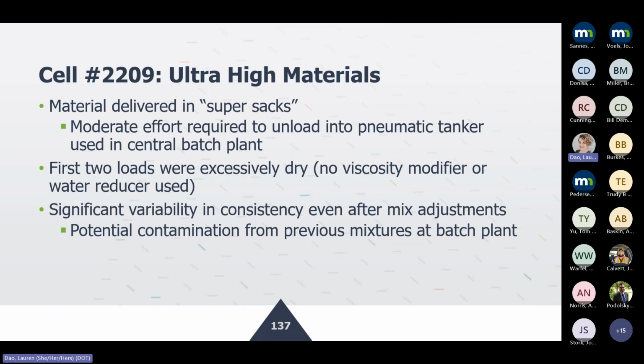But one thing we did observe with this particular material was it loses workability very, very quickly. So I think one reason is we did not have enough time to dial down the mix. This is not to say that this is not a good material, but we need to do a lot of trial testing and batching before we really apply it in the field. And there might be another opportunity this year. I don't know if new test cells open up, but that's something I wanted to mention.